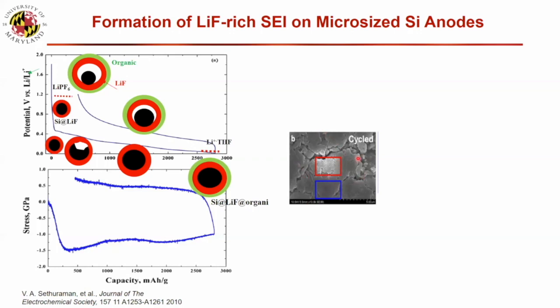This is the lithiated silicon. And then we check if they really have a lithium fluoride or not. We use the beam here to check the surface. This is just a snapshot. And because the beam damage of lithium fluoride is really serious,